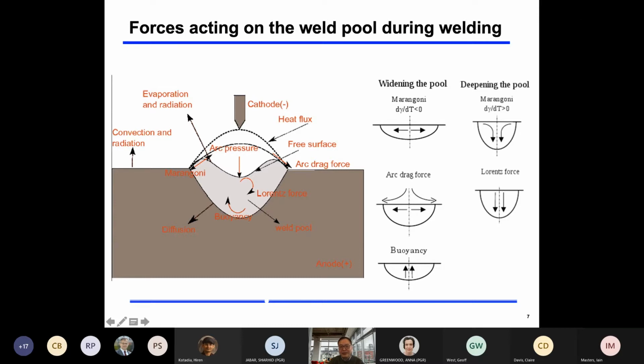So if we group those forces: when the Marangoni force, when your surface tension against temperature change is less than zero, you will have a widening force. And arc drag force is always actually to pull your pool, widen it. Similar to the buoyant force, this is the force acting internally or on the surface or internally in the metal pool. Deepening the pool: look into many Marangoni forces, when surface tension increases as temperature increases, or Lorentz force. Again, it tries to deepen the pool, right?